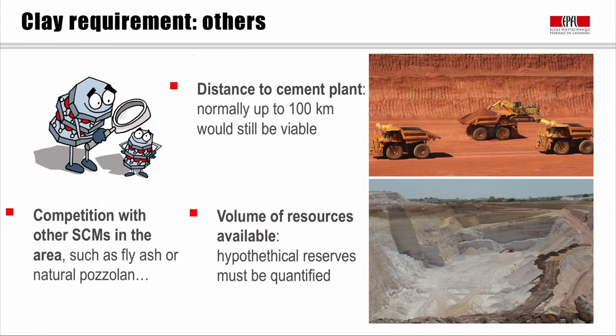What are the other requirements for our clays? Clearly a very important one is to know if there are other sources of supplementary cementitious materials in the area, because if we have fly ash, this is a resource that should be used rather than exploiting new clay. Similarly, natural pozzolans can also work well with cement. Fly ash and natural pozzolans have the advantage that they don't need to be calcined, generally making them cheaper than calcined clays. Distance to the cement plant is important, but distances up to even 100 kilometres can be viable based on preliminary economic analysis. And if you're going to exploit a new resource, you need to work out how much your reserves are and whether the operation can continue for a long time.